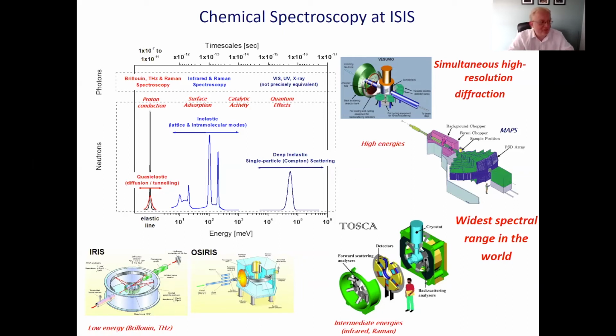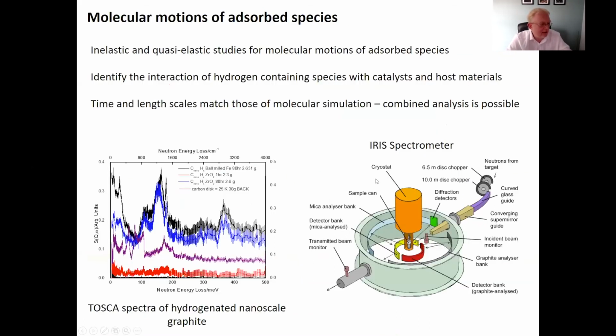And that one significant difference is that because it's a momentum transfer process, there are no selection rules associated with the spectroscopy, which means we're not limited by the point group or space group of the material that we're looking at. All of the vibrational modes will be activated by the momentum transfer. And that allows you to look at some very interesting things.